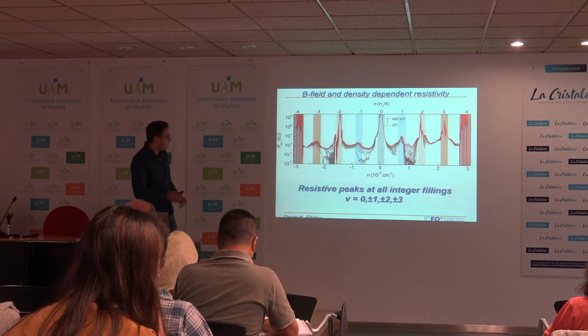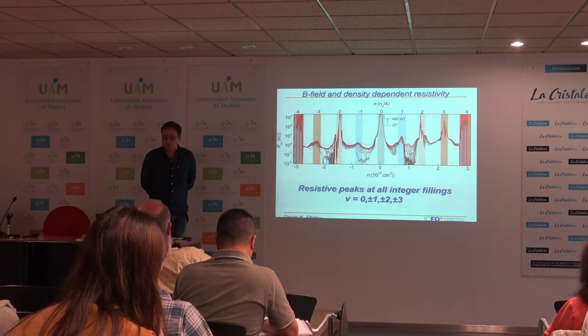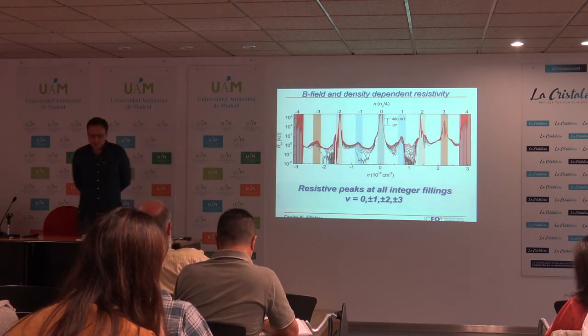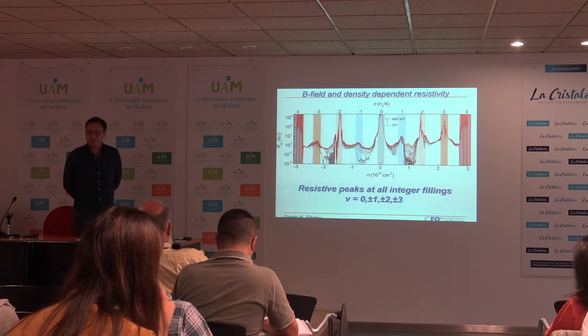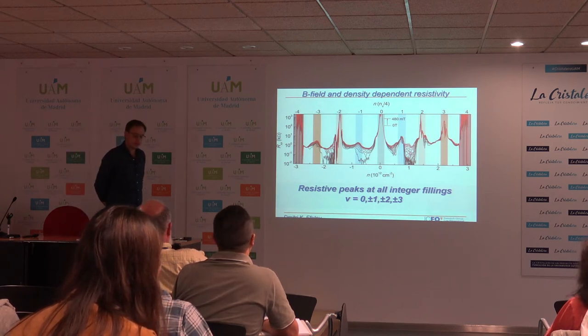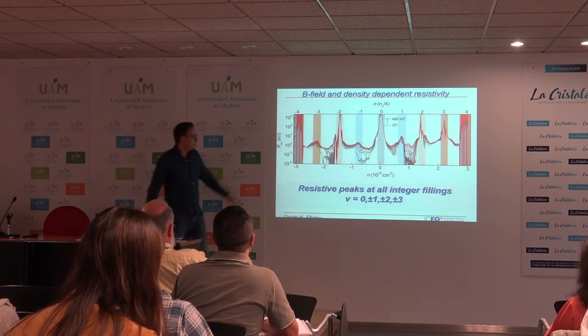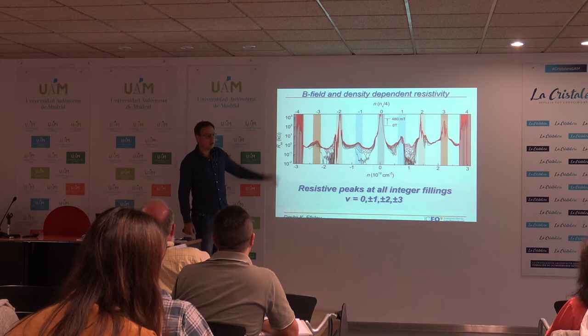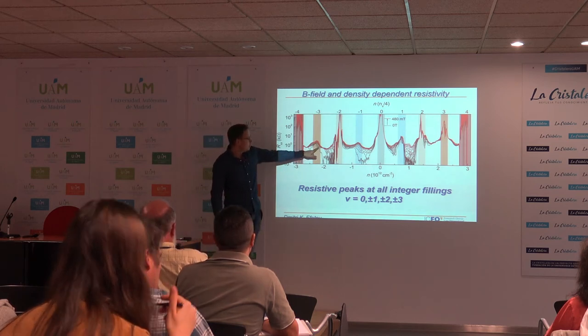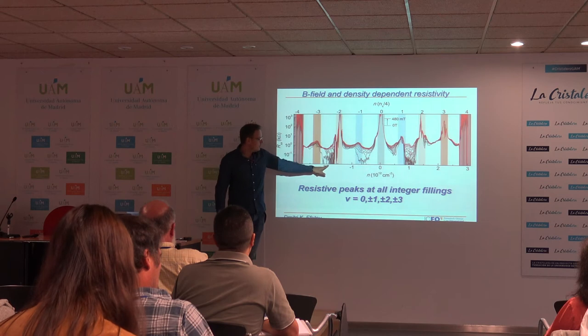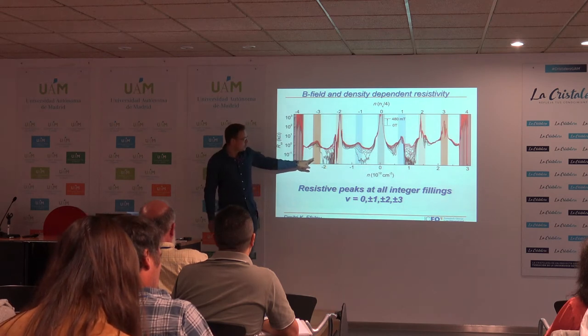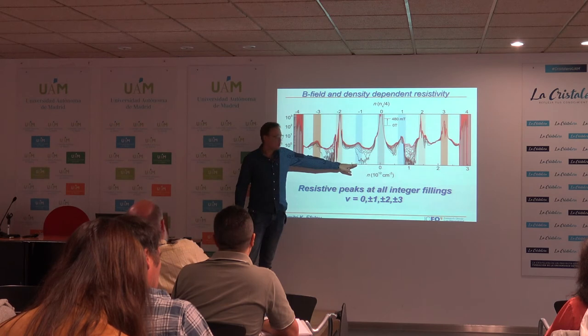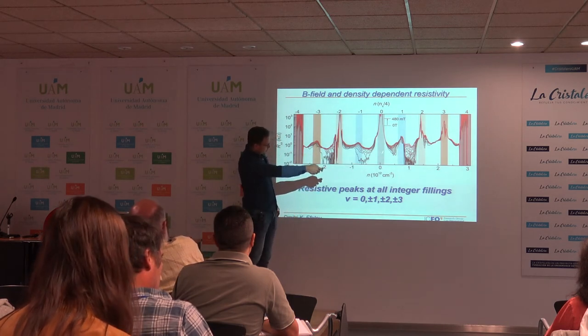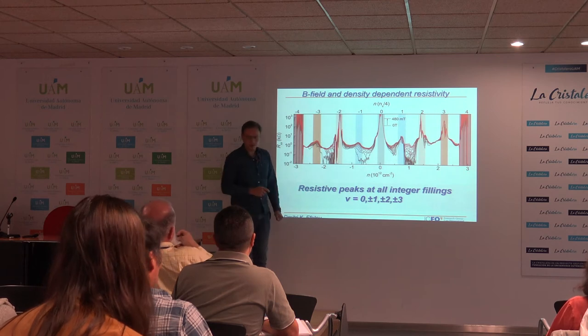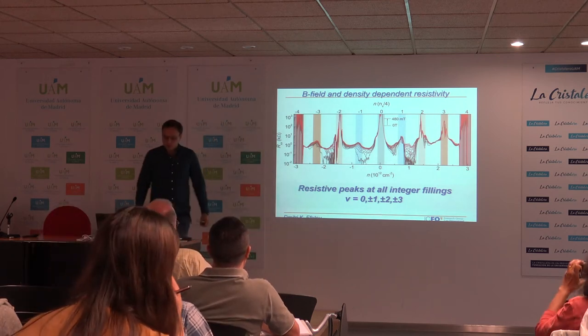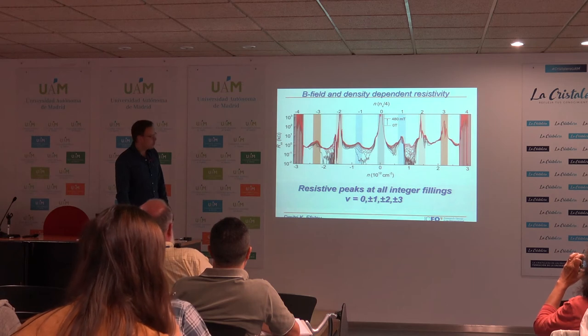Okay, and then the other thing which you also notice from this measurement is that not only do resistive peaks appear in many different locations in the phase diagram, but also these zero resistance states appear in many other different regions. So for example, here between -3 and -2, we have a resistance that drops to zero, but it also does so between -1 and 0. And it also does so between 0 and +1, and also here. So in principle, not only do we see more insulating states, but we also see more of the superconducting state.